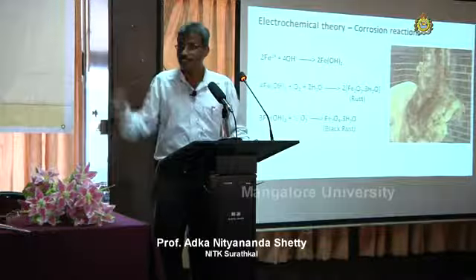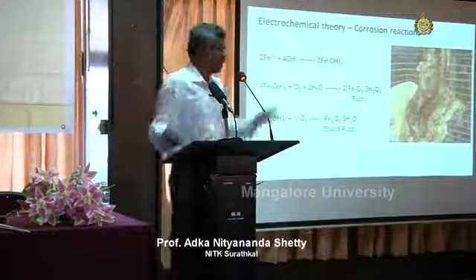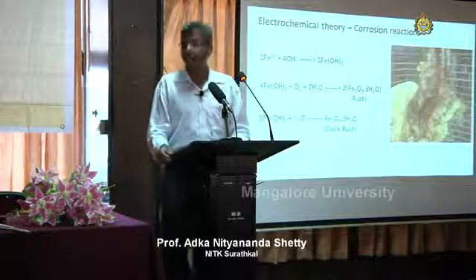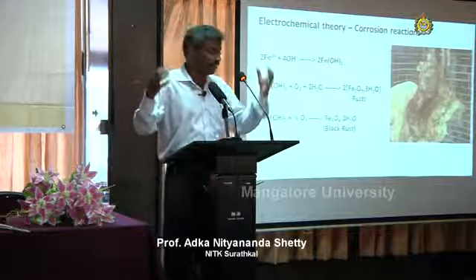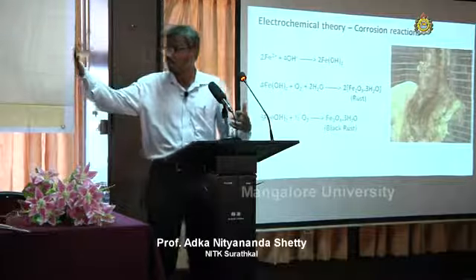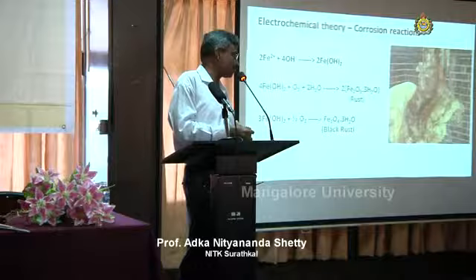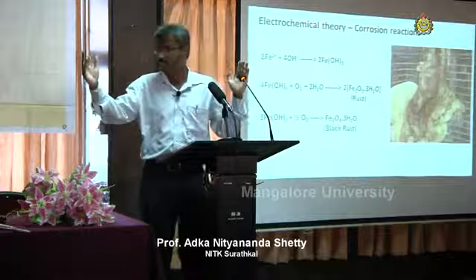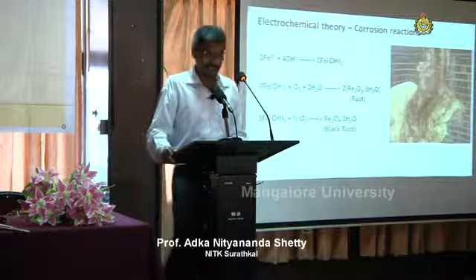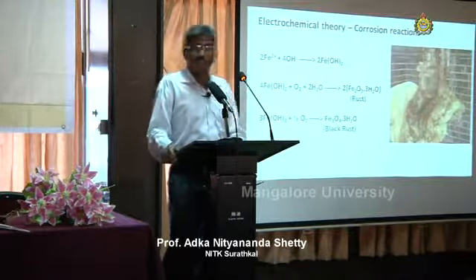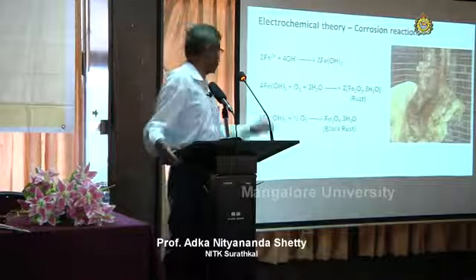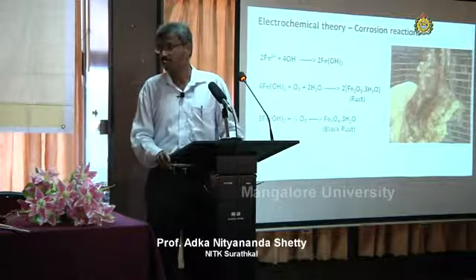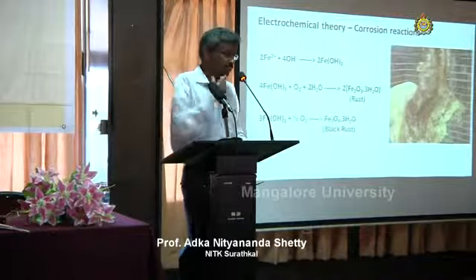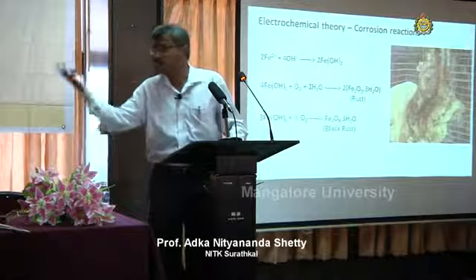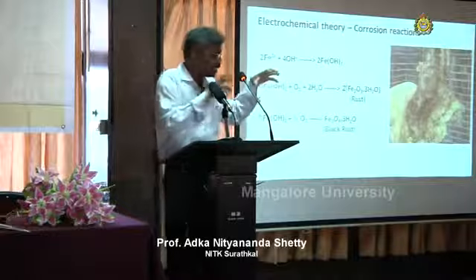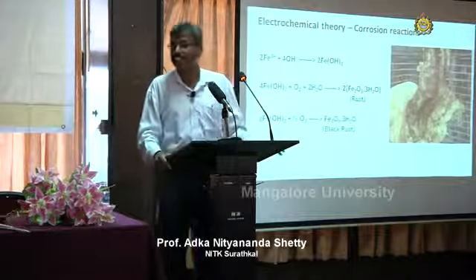If you take iron as an example, at the anode, iron gets converted into ferrous ions. At the cathode, OH minus ions are formed due to the cathodic reaction. Then the ferrous ions from the anode and OH minus ions from the cathode will diffuse towards each other. Somewhere in between the cathodic and anodic region, they combine together to form ferrous hydroxide. And it doesn't remain as ferrous hydroxide. In the presence of sufficient oxygen, this ferrous hydroxide will be further oxidized into hydrated ferric oxide. That is what we generally see as yellow rust. Yellow layer on the steel surface, yellow rust, that is hydrated ferric oxide.